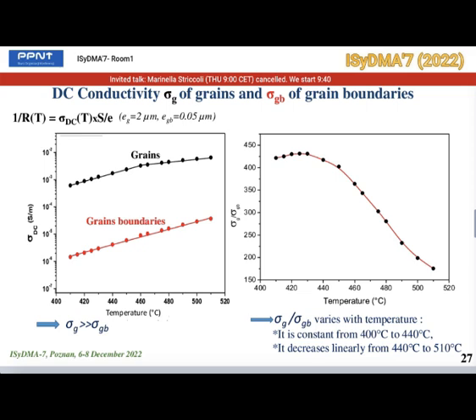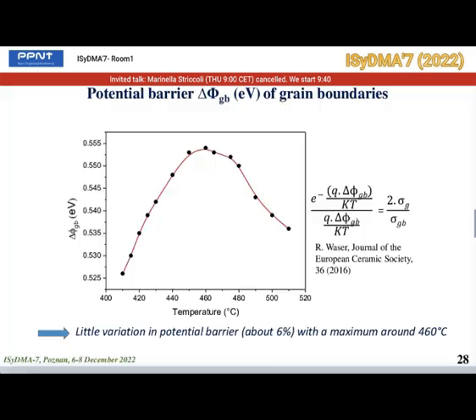We then deduced from the software calculations the values of the DC conductivities of grains and grain boundaries, because they are inversely proportional to the resistances calculated by the software. We can notice that grains conductivity is very large compared to that of the grain boundaries, although the ratio decreases when the temperature increases beyond 440 degrees.